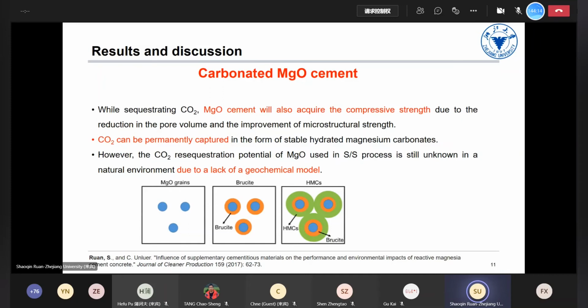You can see from this figure that MgO will first react with water to produce layers of brucite on the surface of the particles. Then it will further react with carbon dioxide to produce the HMCs, that is, the hydrated magnesium carbonates. And then this leads to the reduction of pore volume and to strength improvement.